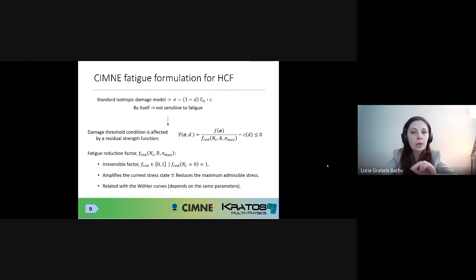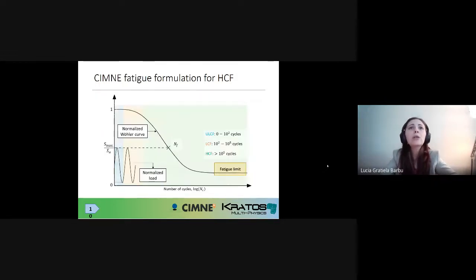And the expression of this reduction function is related 100% with the Wöhler curves, with the stress-number of cycles curves. What do I mean by related? I mean it depends on the same material parameters that you have to calibrate. So if we take a look, for instance, at a typical SN curve, normalized with the maximum tensile strength, we see that for a specific level of maximum loading, what the SN curve gives us is the maximum fatigue life that the material can withstand at that stress level.